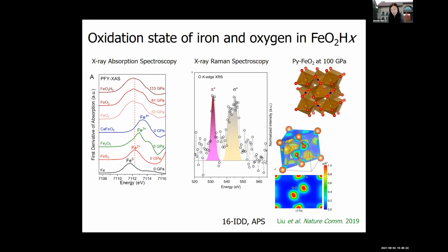So we also conducted an X-ray Raman spectroscopy study to look at the oxygen edge for this compound. Now, this is a very challenging measurement since we cannot access the oxygen edge directly through X-ray absorption. At 540 eV, the oxygen edge is a soft X-ray measurement and requires vacuum. So we have to do an inelastic measurement and shift both the incident and the scattered X-rays into the hard X-ray regime. And then the difference in the incident and scattered X-ray energy is the oxygen edge. So here, this is the measurement we did on the oxygen K edge for FeO2 at 110 GPa, I think. And the thing to notice here is that you see a significant pi star peak, which would be consistent with increased oxygen-oxygen interactions and the oxygen being more oxidized.